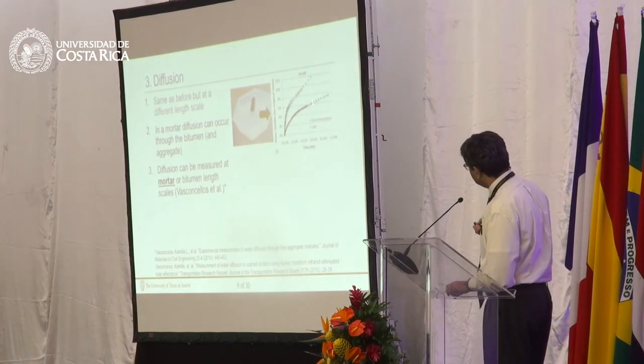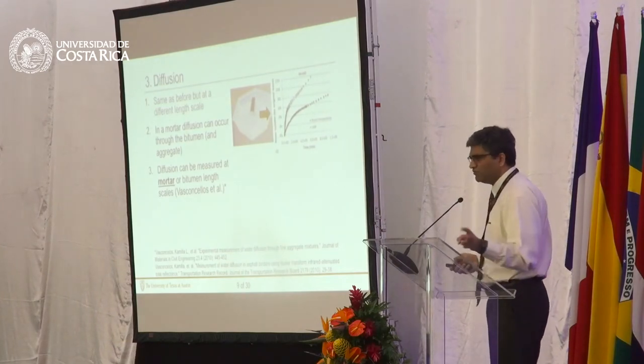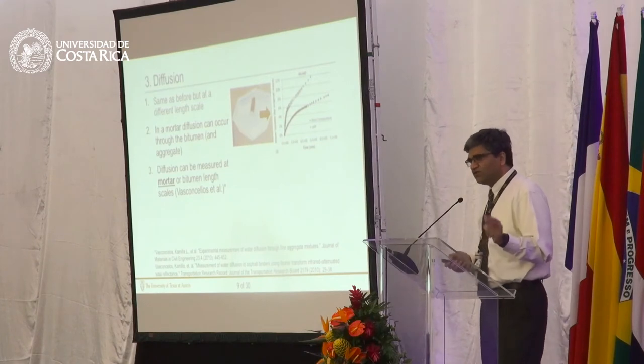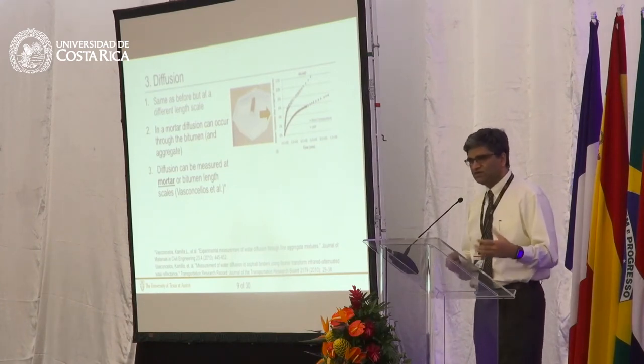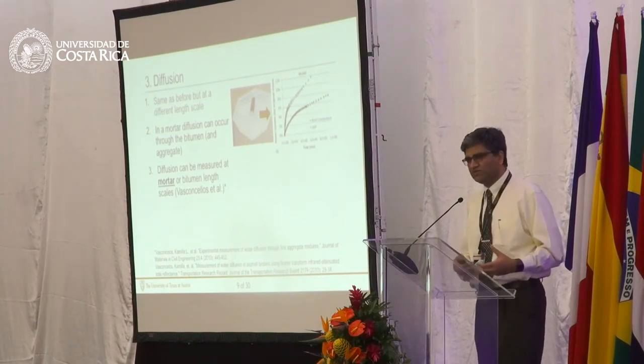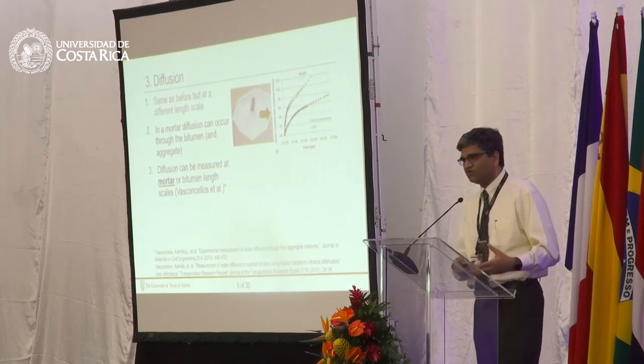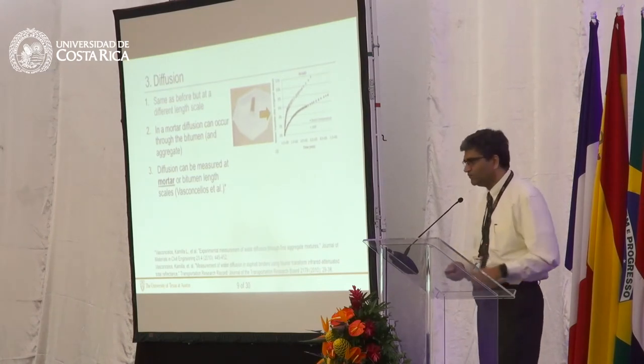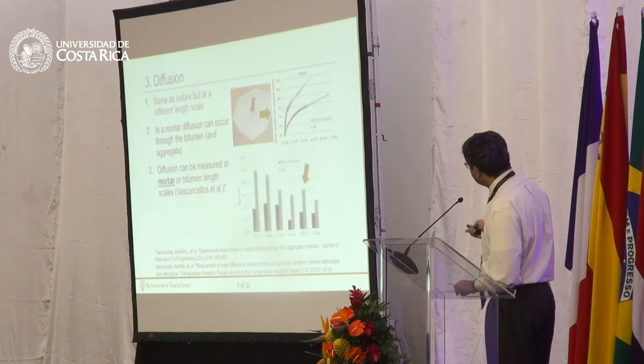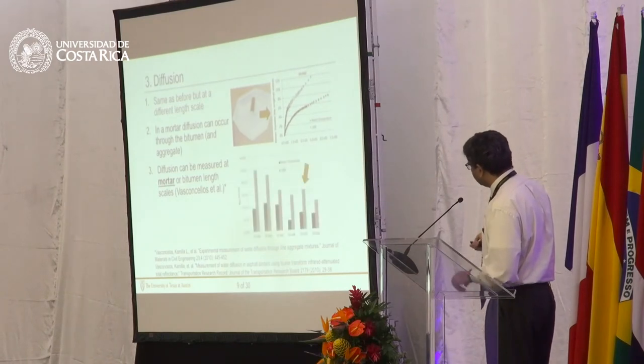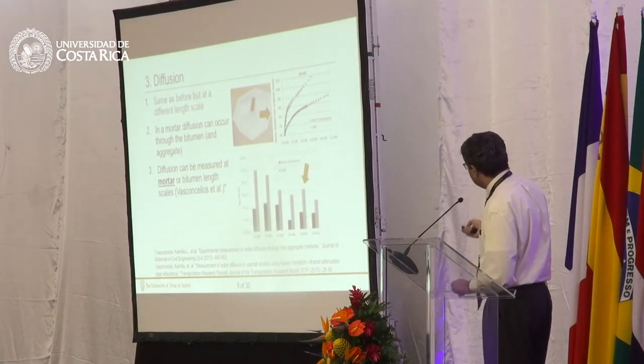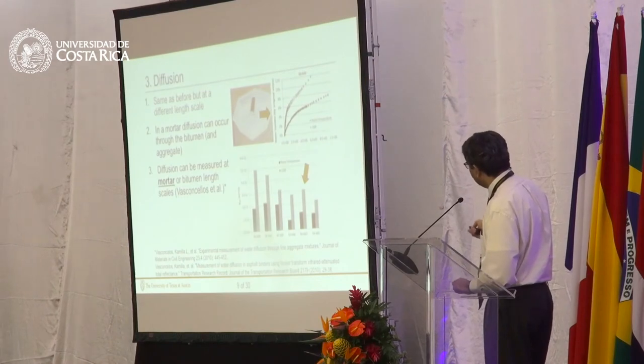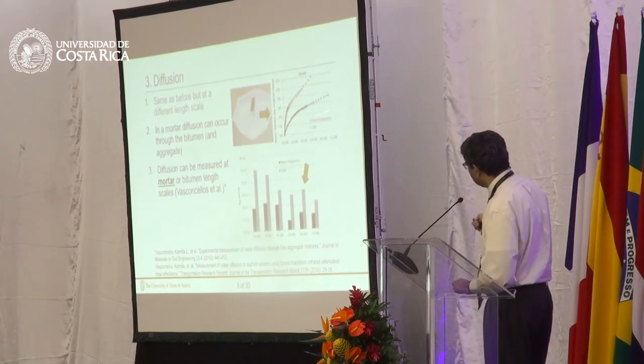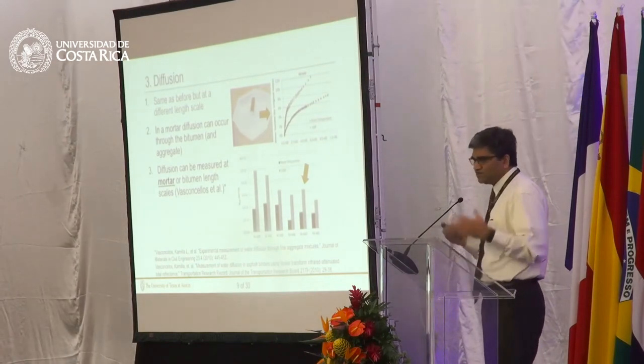Once you have the weight recorded as a function of time, in this case, it's the same mortar, except that the diffusion was being measured at two different temperatures. One of the temperatures was a high temperature because oftentimes in moisture damage tests, we try to accelerate the moisture damage process by heating the water. This is not the place to go over all the equations, but this is basically a Fickian diffusion model, and it's a textbook solution.